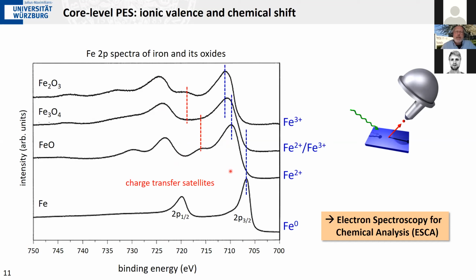And the second effect is that we don't just have non-interacting electrons. The 2p electrons interact with the 3d electrons by Coulomb interaction. It turns out if you look at the radial distribution of the wave functions, the 2p's and the 3d's have some spatial overlap, and so there is some Coulomb interaction going on, so that we get multiplet effects between the partially occupied 3d shell and the 2p shell in which we now have created a core hole. And this gives rise to multiplet effects, and these are reflected in these line shapes. So as you change the filling of the 3d shell by going to higher and higher valency, you see characteristic changes in this multiplet structure.